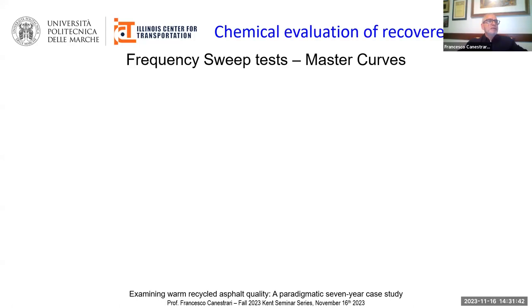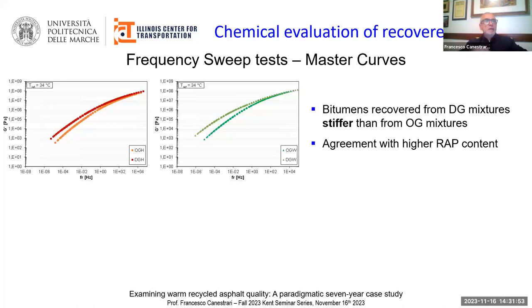The recovered polymer modified binders from both warm and hot mixtures were also subjected to frequency sweep tests to obtain the master curves. Looking at the pictures, it's clear that bitumens recovered from dense-graded mixtures are stiffer than the ones recovered from open-graded mixtures. This result is in agreement with the higher RAP content used for the production of the dense-graded mixtures, equal to 25%, whereas for open-graded mixtures, RAP content was only 15%.